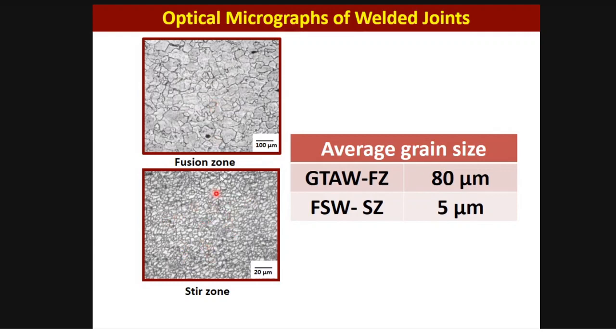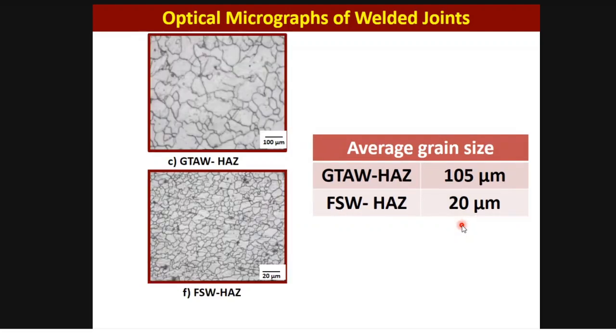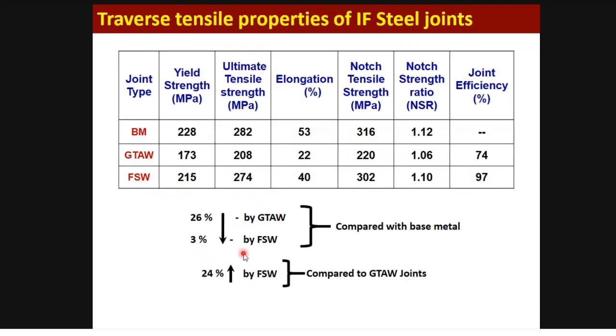You see the difference in the grain size. So here it is 80 microns average grain size in GTAW, and in FSW it is only 5 microns. A very fine grain formation, due to the dynamic recrystallization effect in this friction stir welded joint. Again, that effect is there in the heat affected zone also, finer heat affected zone, and in the GTAW it is coarse, very coarse. You see that is 105 microns here. Here it is only 20 microns.